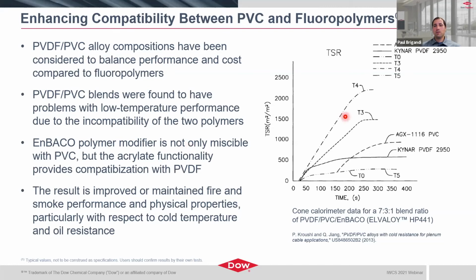But at the same time, what I show on the right-hand side is a plot from the cone calorimeter on total smoke release rate again. And what you find is that at a given ratio of 7:3:1, so that's PVDF to PVC to modifier, when you compare the performance to the base components themselves, so PVC, PVDF, as well as a couple other compositions, the key ones to focus in on based on that ratio are the T0 and T5. And those were both shown to have more improved smoke release performance. So much lower than even the polymers themselves.